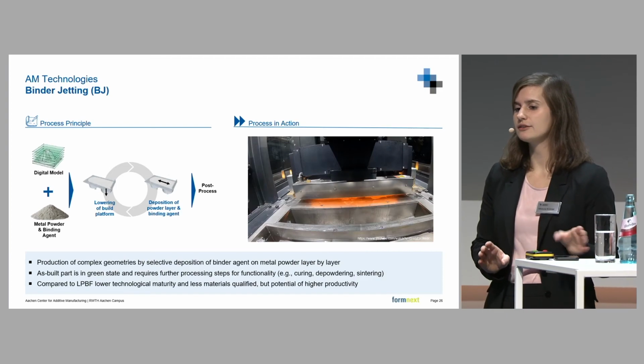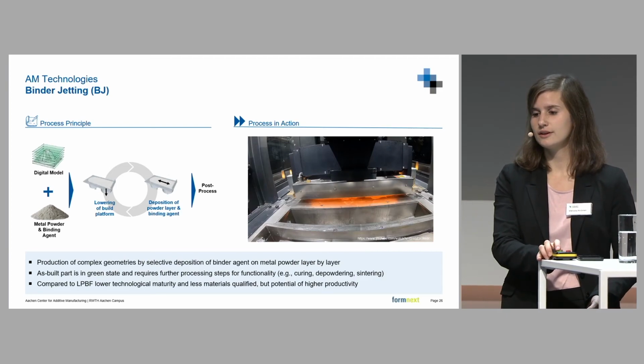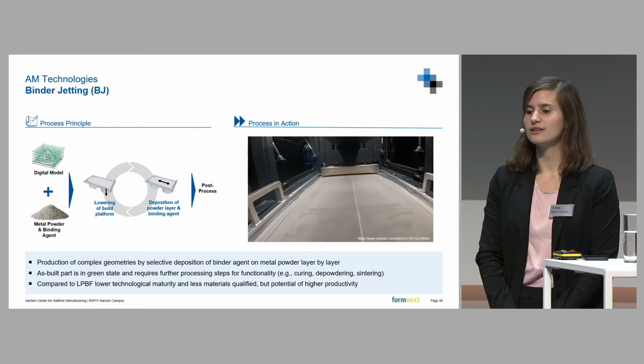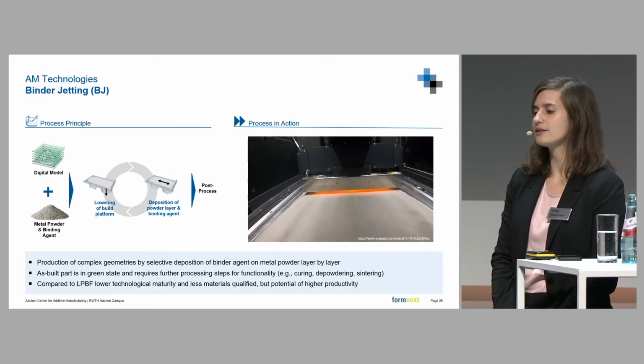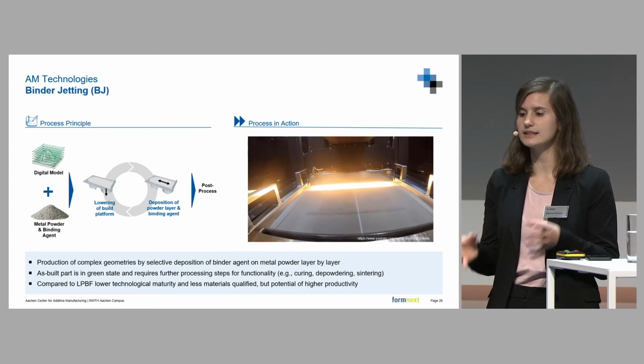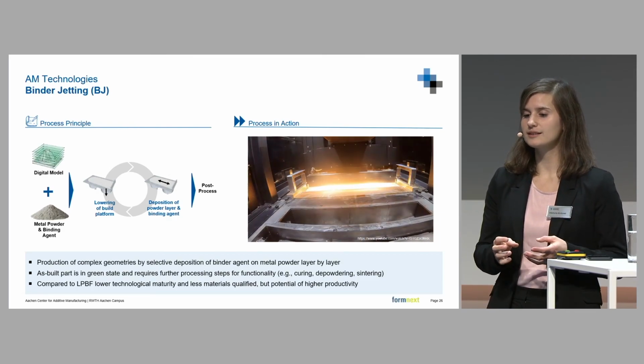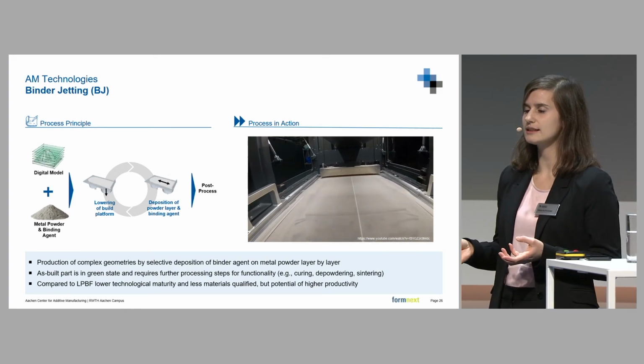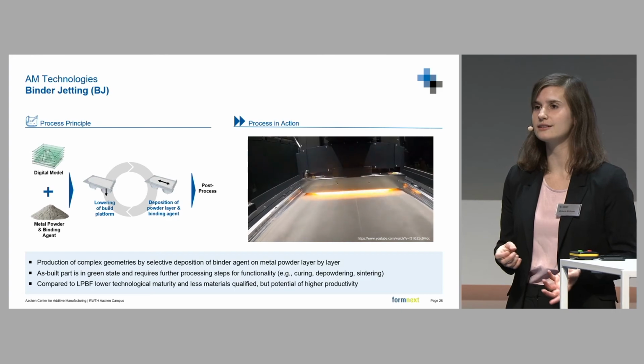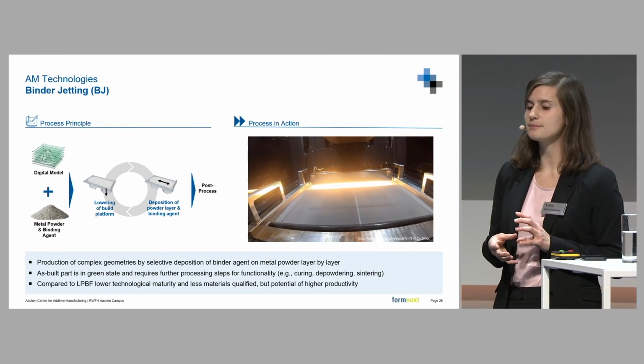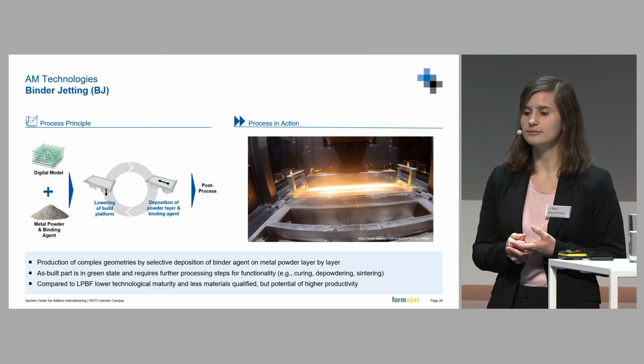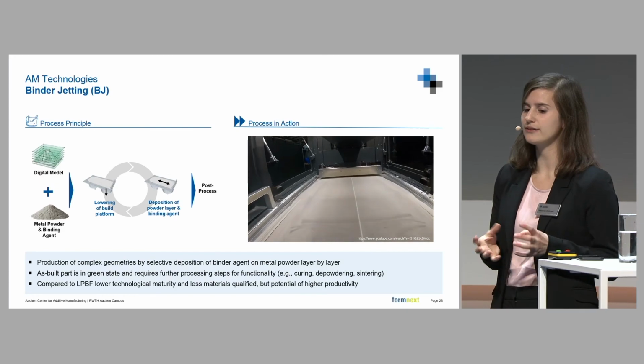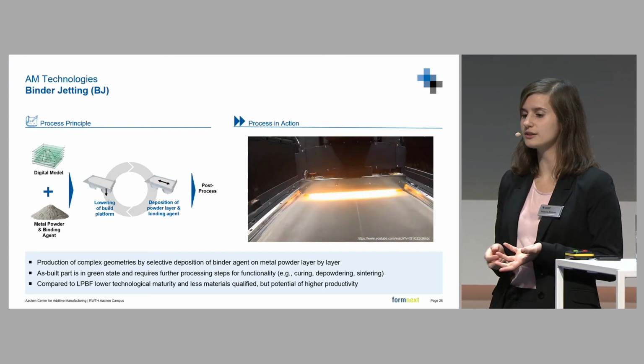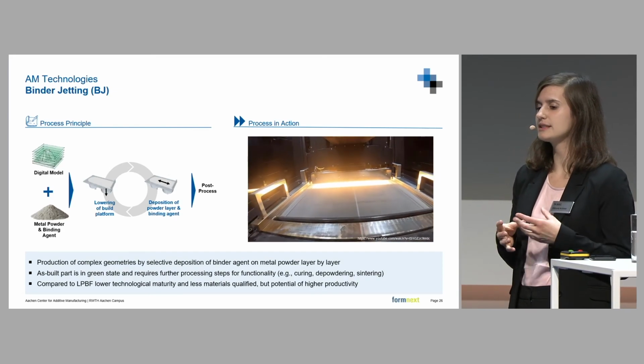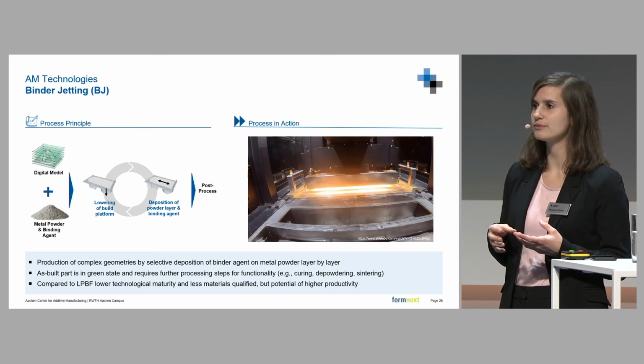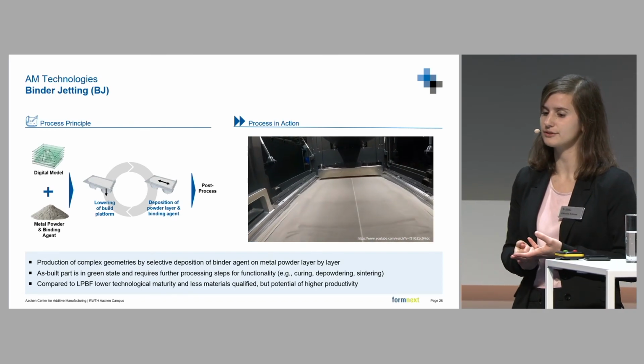So now for the last part of the live stream, let's look at binder jetting. Like laser powder bed fusion, you have a metal powder bed, so you have powder that's deposited layer by layer, and the digital model as input. The way it works is the build platform is lowered, powder is deposited, and then a binding agent is applied. So instead of putting a laser or an electron beam on top, you fuse the part by applying a binding agent. Binder jetting has the advantage that you are able to process very complex geometries. You don't need any support structures for that technology. And you can nest the parts three-dimensionally within the build chamber, so you're able to place many more parts inside compared with laser powder bed fusion.